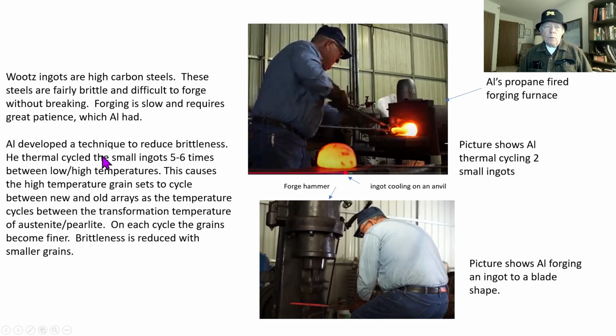He thermal cycled small ingots 5 to 6 times between high and low temperatures. This causes the high temperature grain sets to cycle between old and new arrays, as the temperature cycles between the transformation temperature of austenite at high temperatures and pearlite at low temperatures. On each cycling, the grains become finer, and the brittleness is reduced with finer, smaller grains. So that's how his technique worked. Now here's a picture of him doing it.